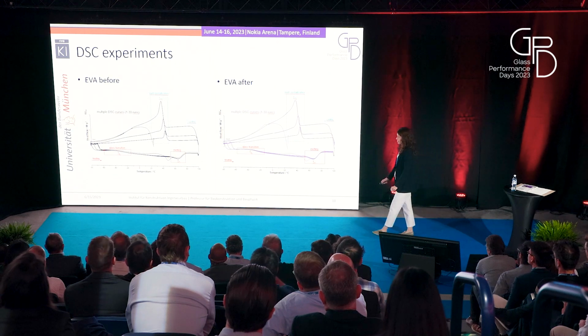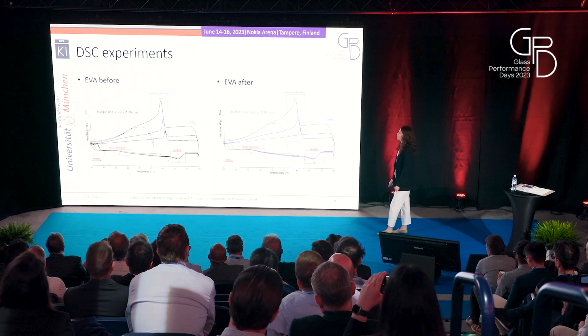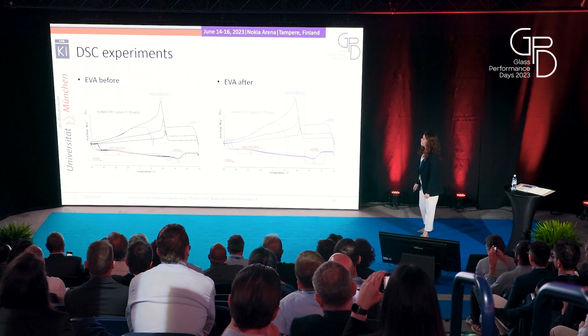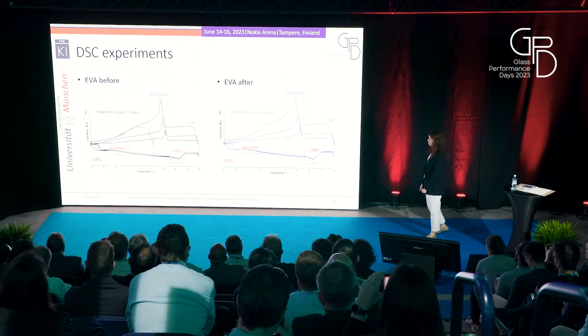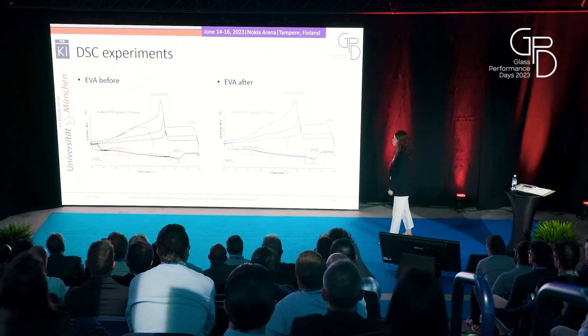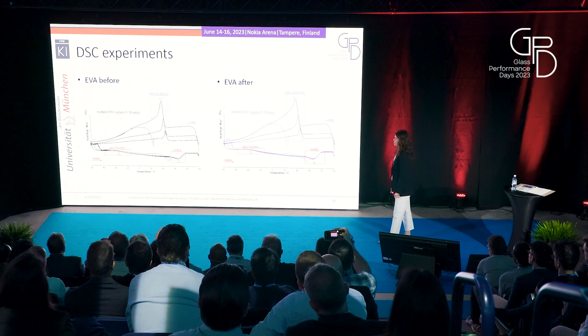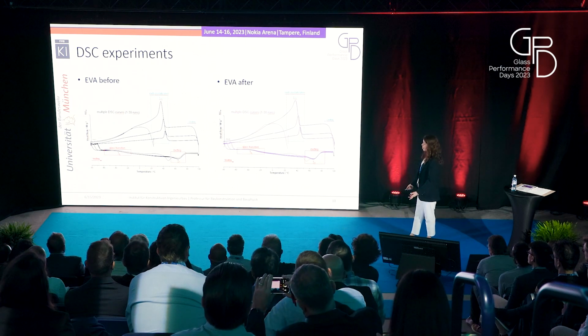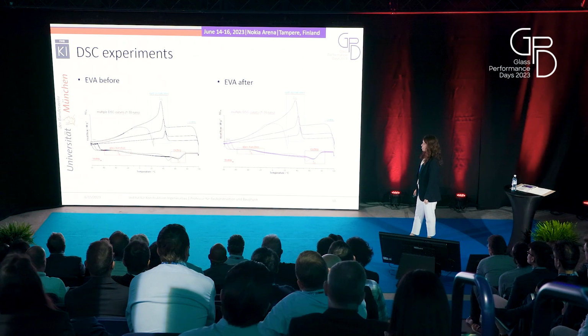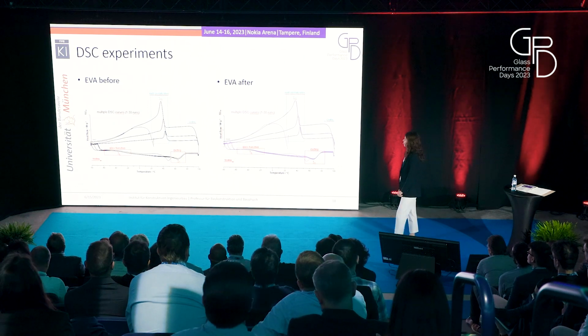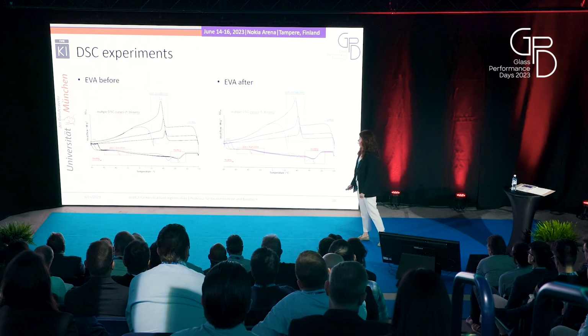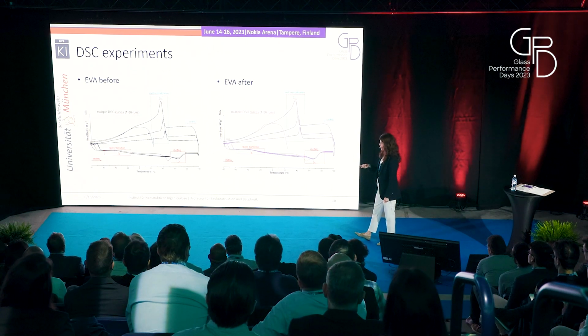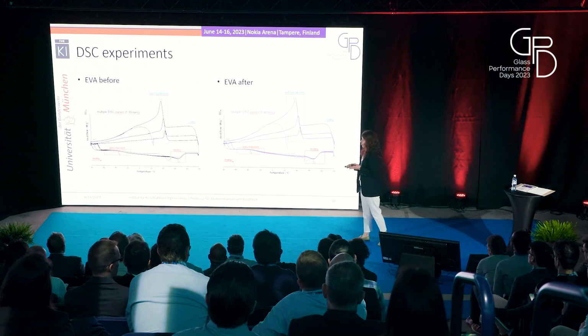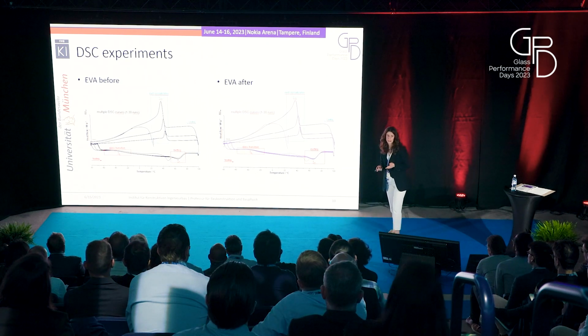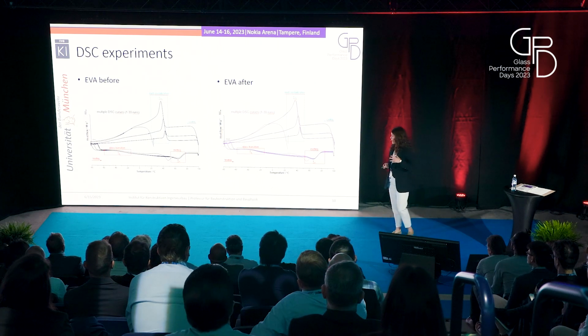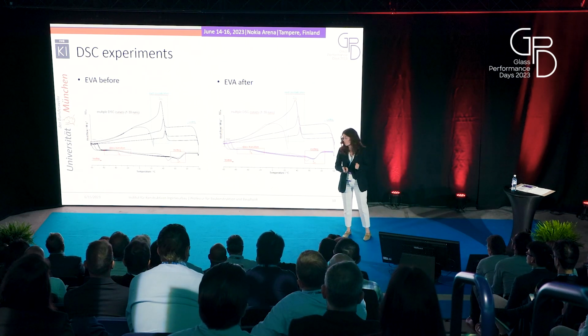And now let's go to our results. Here are the results of the differential scanning calorimetry experiments, and on the left are the results of the EVA interlayer before they were exposed to a humidity program, and here are the results of the EVA after. The X axis of both of these diagrams shows the temperature range that we used for this test, from -80 up to 100 Celsius.